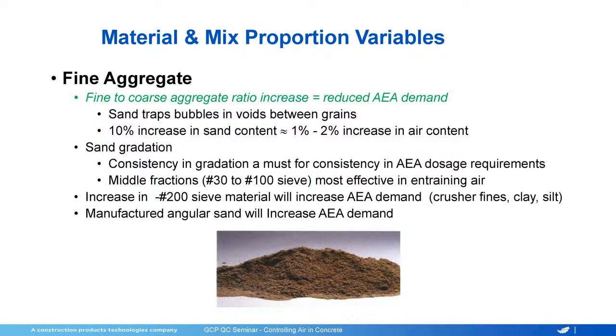Fine aggregate, and this is really, if I had to say which material I can control to make the biggest impact on the air, I would say if you're dealing with a decent fly ash, it's going to be the sand. If you have a crappy fly ash where the carbon's all over the place, then it's going to be the fly ash. In either case, a consistent sand gradation is going to be a huge help. Now, yes, if you're using natural sand, it's easier to get air than with manufactured sand. But in both cases, if you can have consistent gradations, that is the key to having the right air entrainment.